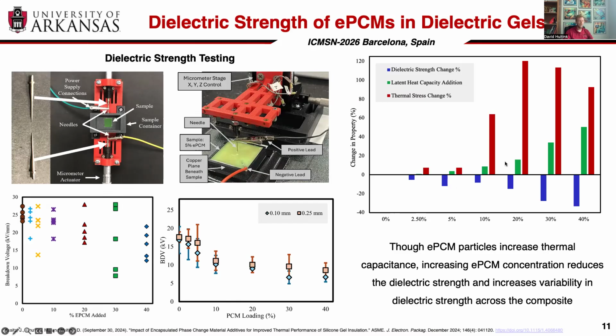We do see an improvement in the thermal storage, energy storage here in the green bars. But that comes along with some of these stress effects, as well as some of these voltage reduction effects. So it really comes down to tuning the mixture of the composites to accommodate the multiple requirements, electrothermal and mechanical aspects in electronic assemblies.